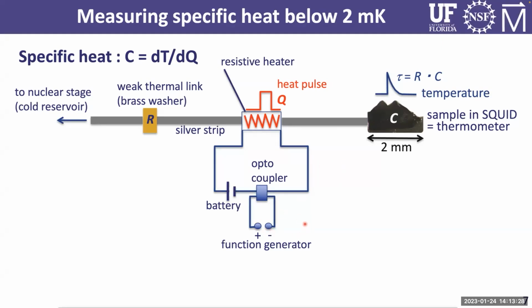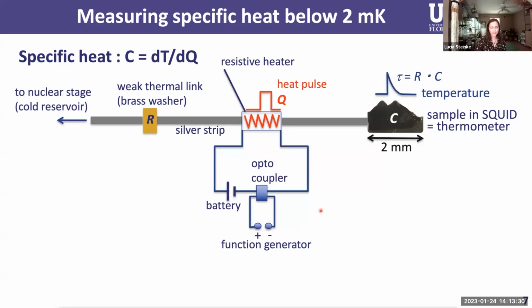There are basically two issues here. The first is heat leaks. Heat leaks are everywhere if you're working at 2 millikelvin. And one particularly difficult source for a heat leak was our function generator that was used to apply heat pulses to a heater. And if we had this directly connected, it was putting so much heat into our sample, even if we are not applying a heat pulse, that the sample was just staying way too warm and we didn't see the transition.